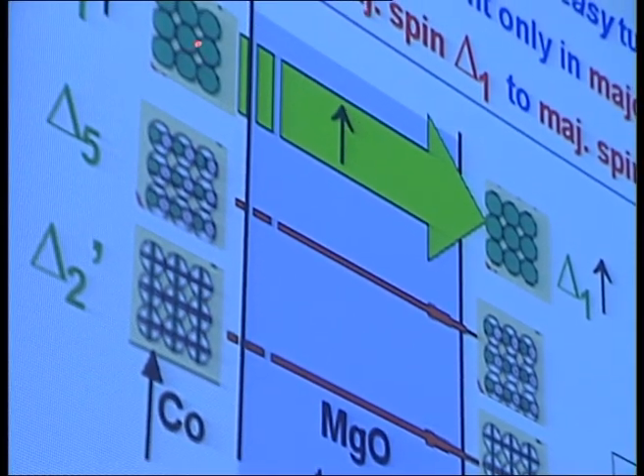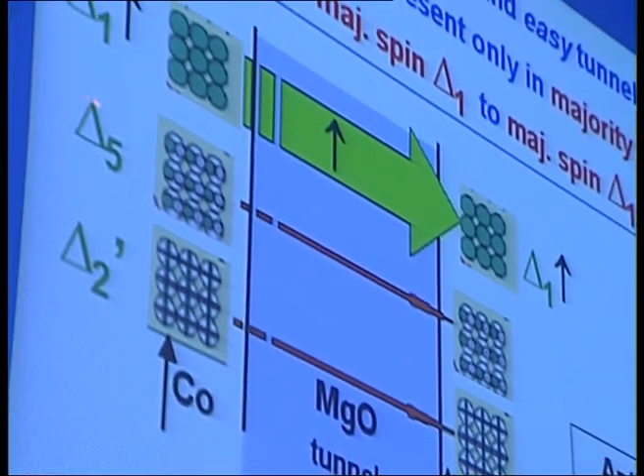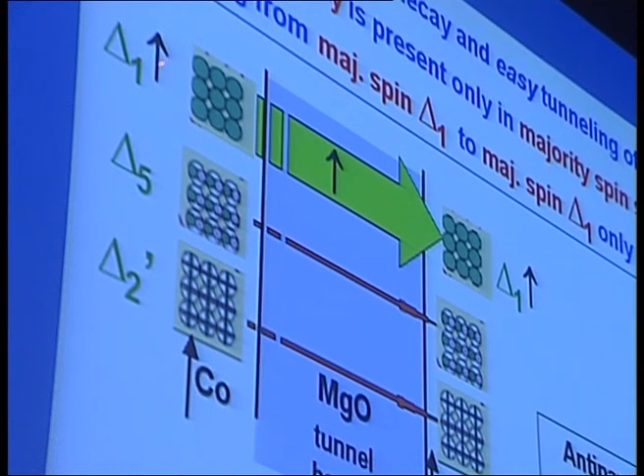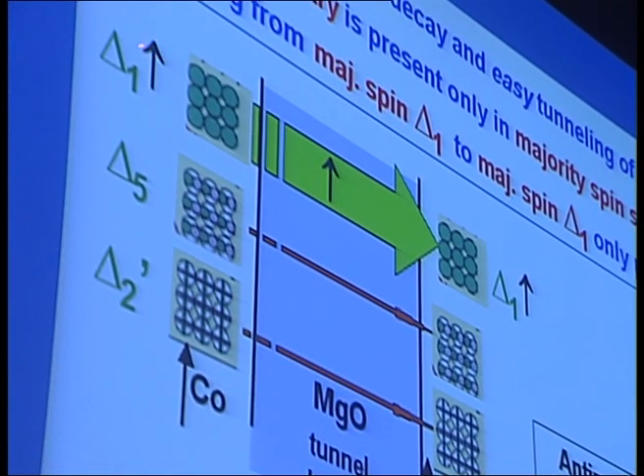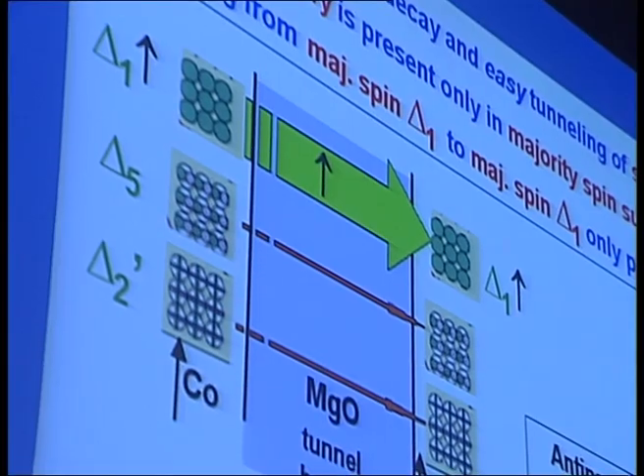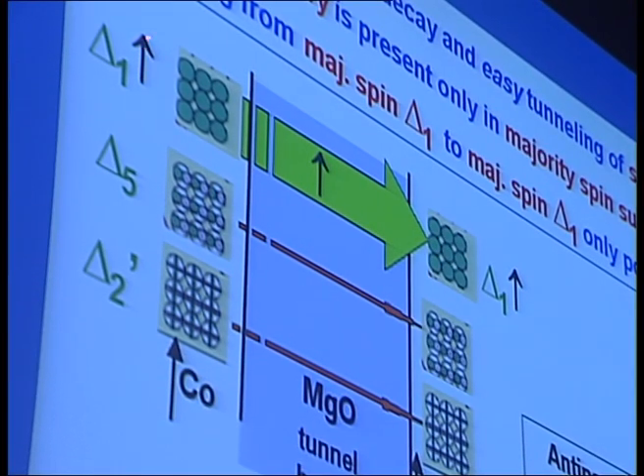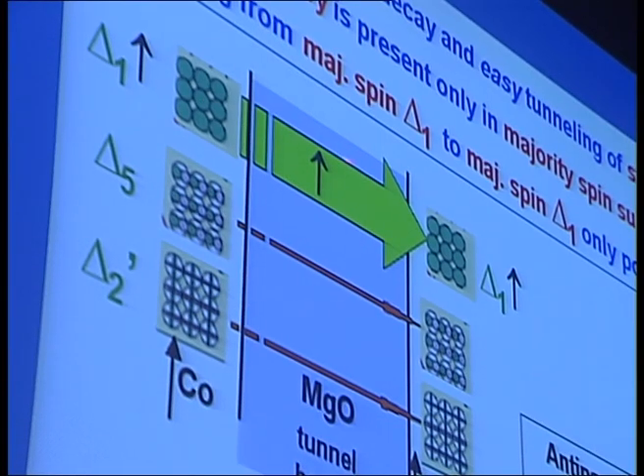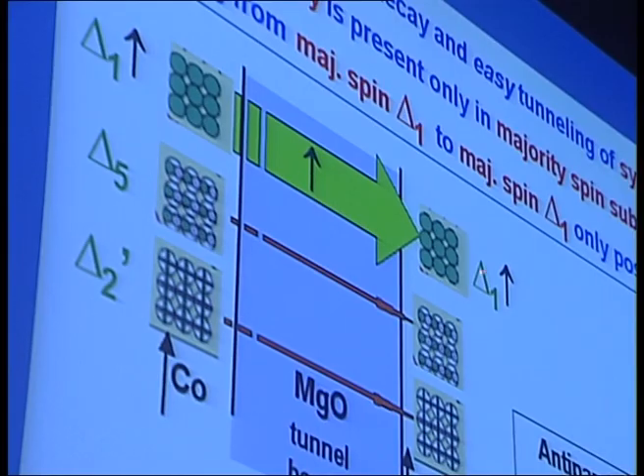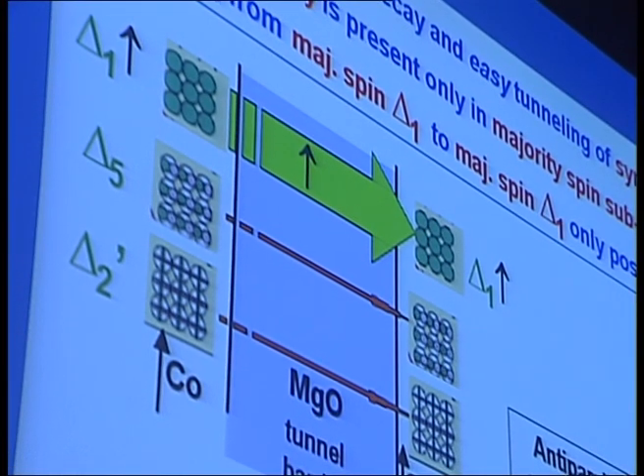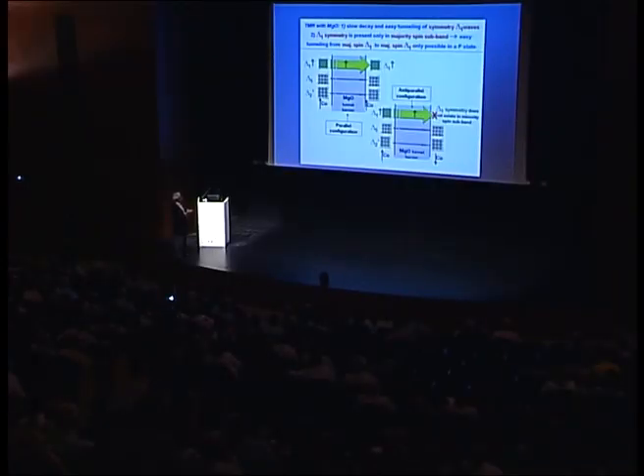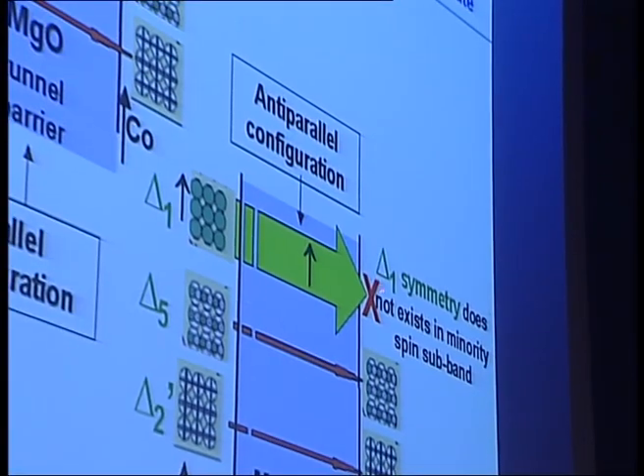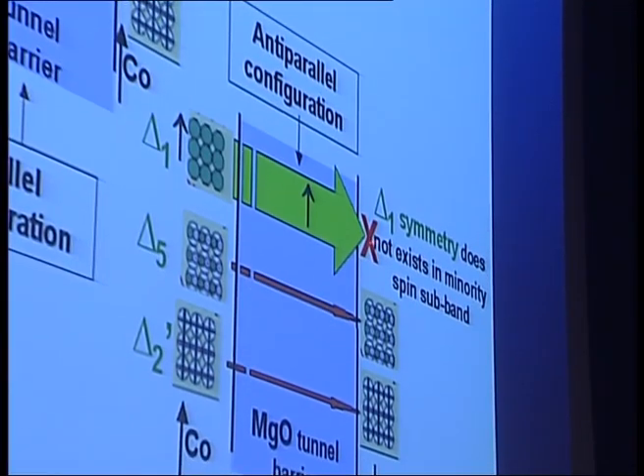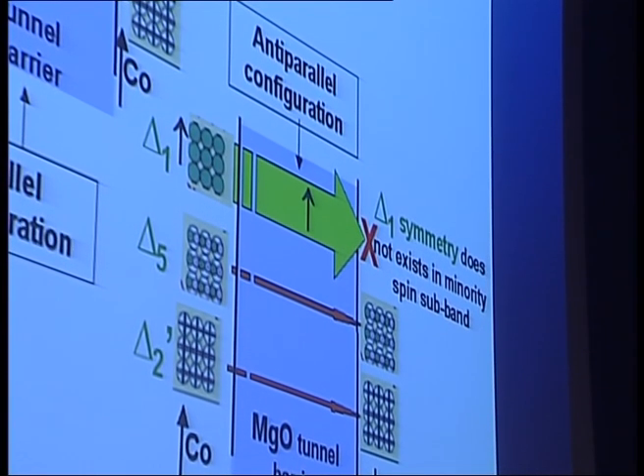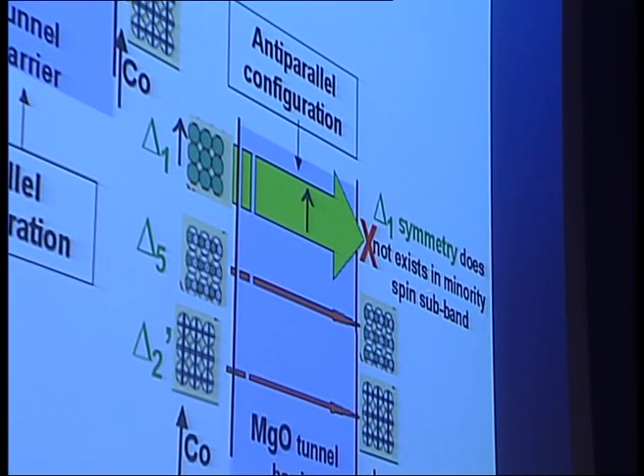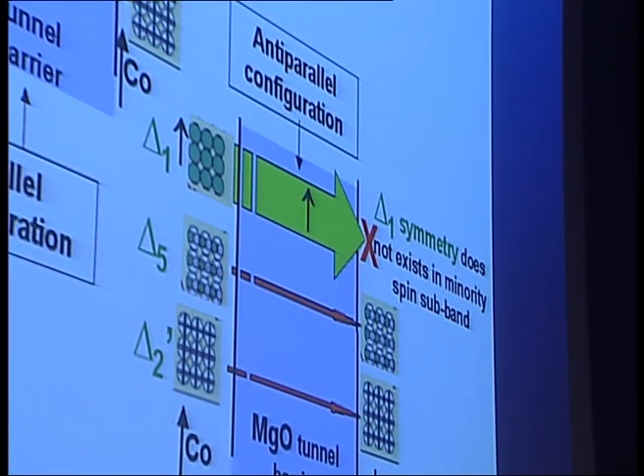And so the key point is that the symmetry delta 1 is present in the majority spin subband of cobalt, but not in the minority spin band of cobalt. So there is no problem when the configuration of the two layers is parallel: then a majority spin, delta 1 symmetry electron can go through the channel and be accommodated in a state of symmetry delta 1 of the majority spin subband. But when the configuration is anti-parallel, this electron, when it comes into the other electrode, is in the minority spin direction because this magnetization has been reversed, and there are no states to accommodate it, and the current cannot go through the channel. And so the resistivity is much higher.